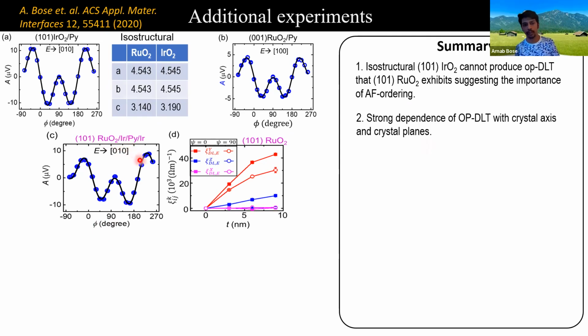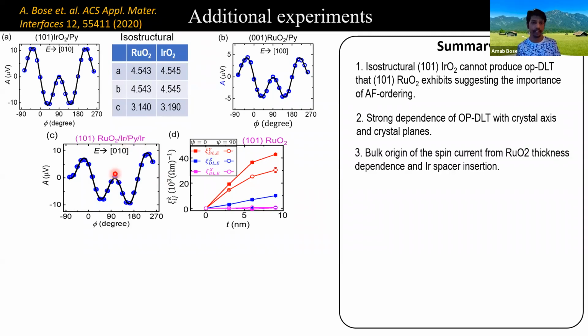We inserted iridium as a spacer. In this case, we found that the angular dependence, the extraordinary spin torques have gone down, but still it is present. It is non-zero. But its magnitude has gone down because of the spin attenuation through the iridium that has a small spin diffusion length, suggesting that it is bulk in origin.